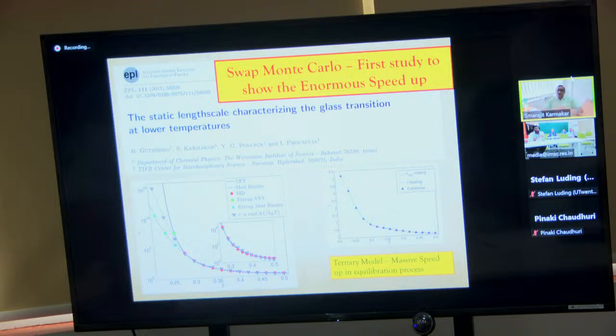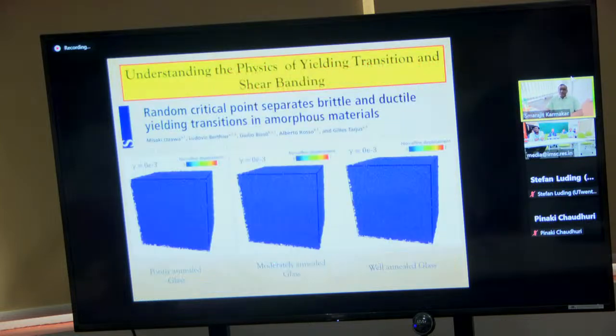And using that, we looked at various dynamical and static properties, particularly computed the static correlation length, and found for the first time that the static correlation length in this system can grow by at least a factor of 5 or 6, which was impossible to achieve before, and all previous literature data showed static correlation length growing by a factor of 2. So this was a significant advancement in terms of how you can access low energy glassy states, which was later picked up in this work, particularly by the group of Ludovic Berthier and his collaborators.